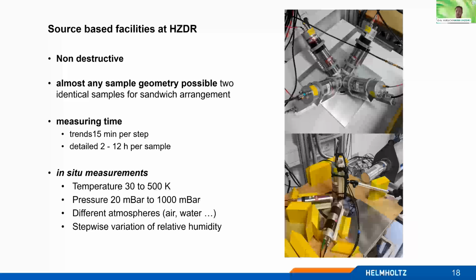And now the parameters we can offer. At the moment, we have these 2 setups. Both are able to measure your material in situ from 30 Kelvin to 500 Kelvin. One of them is also able to vary the pressure in situ from like 1 or 20 millibar to 1000 millibar with or without different atmospheres. So you can use air or humidified water or CO2 or nitrogen. This is up to you and what gas we can offer at the moment.